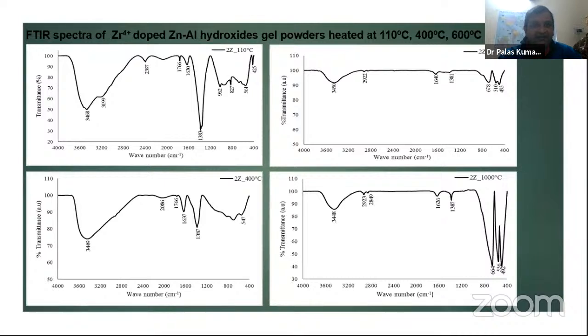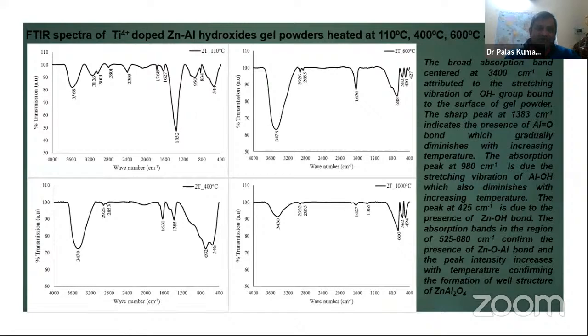Similarly, this is for zirconia. It's the same thing, but here the Zr-O stretching vibration overlaps in the range of 800 to 500 centimeter inverse. So it is not clear, but ultimately at 1000 degrees centigrade a strong Zn-O-Al bond is formed, and the same evidence is also seen from the titanium based matrix.